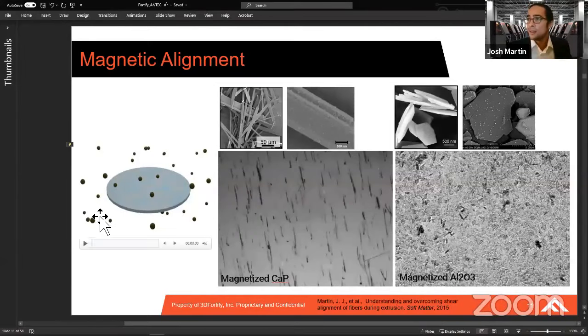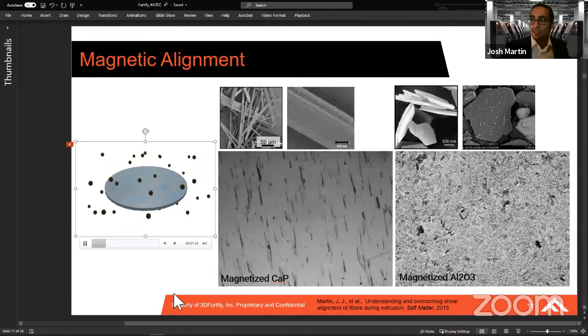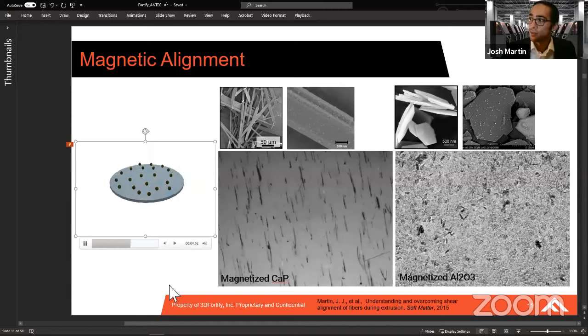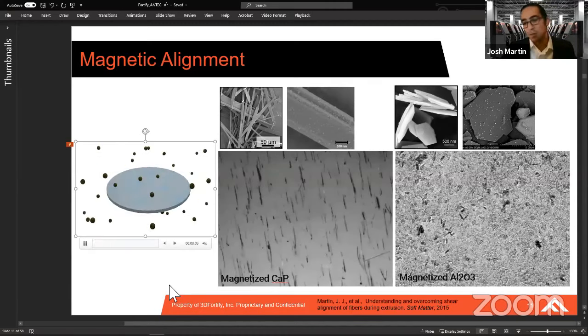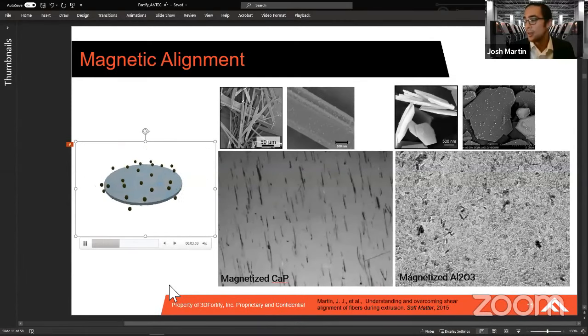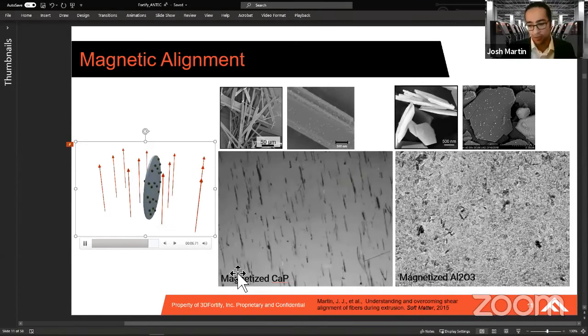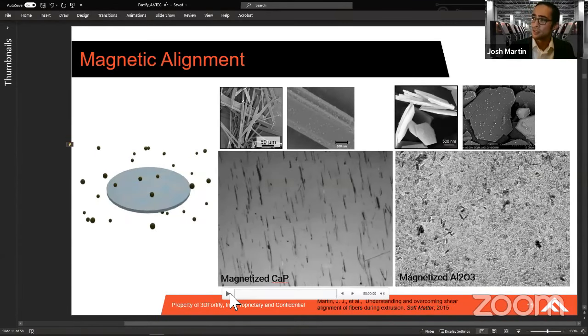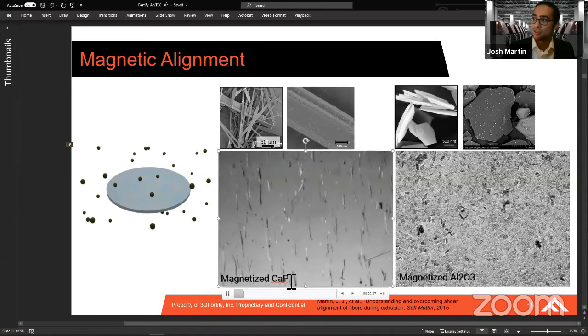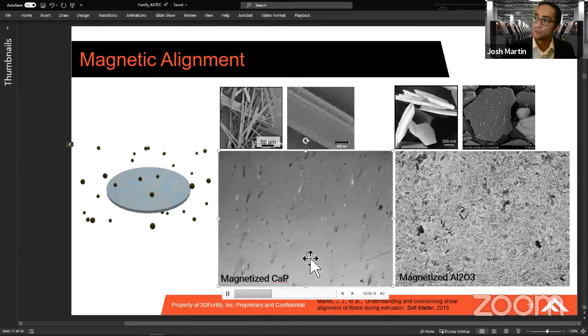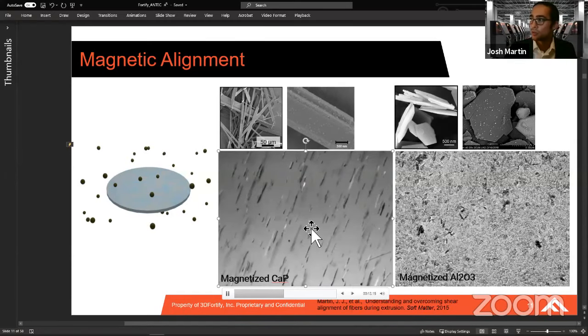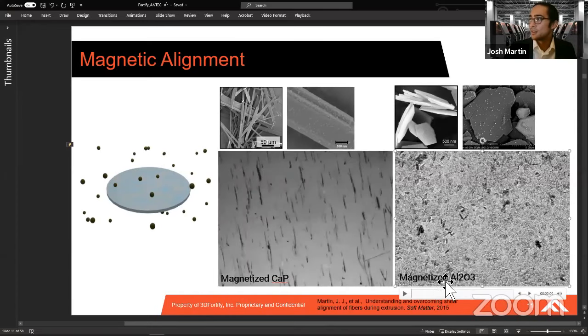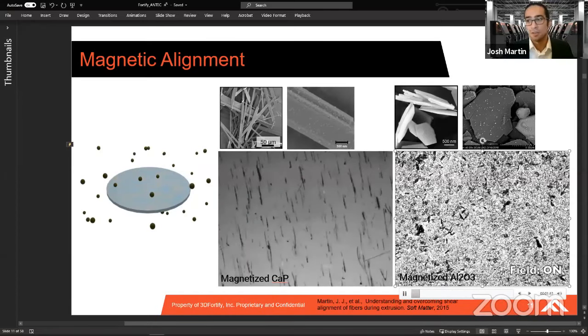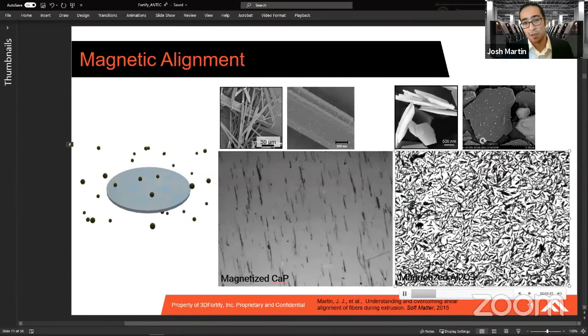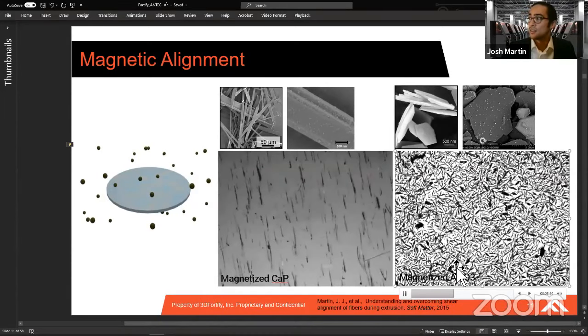Essentially our magnetization technique allows us to coat the surface of essentially any particle we can source, whether it's a ceramic base, metallic base, or some type of polymer. We've done a lot of work with carbon fiber, different types of ceramics such as silicon carbide. And just to show you the nature of this response, this is calcium phosphate, a generally abundant biocompatible ceramic. A field will be applied, it'll switch. You'll see these particles orient within a fluid medium. And this is just another example. We're able to use magnetic fields on the order of a refrigerator magnet using this technique to order these particles.